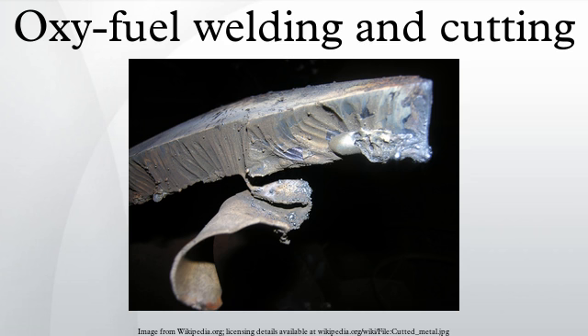The same equipment can be used for oxyacetylene blow torches and welding torches, by exchanging the part of the torch in front of the torch valves. For a basic oxyacetylene rig, the cutting speed in light steel section will usually be nearly twice as fast as a petrol-driven cut-off grinder. The advantages when cutting large sections are obvious. An oxy-fuel torch is light, small and quiet and needs very little effort to use, whereas a cut-off grinder is heavy and noisy and needs considerable operator exertion and may vibrate severely, leading to stiff hands and possible long-term repetitive strain injury. Oxyacetylene torches can easily cut through ferrous materials in excess of 200 mm. Oxygen lances are used in scrapping operations and cut sections thicker than 200 mm. Cut-off grinders are useless for these kinds of application.